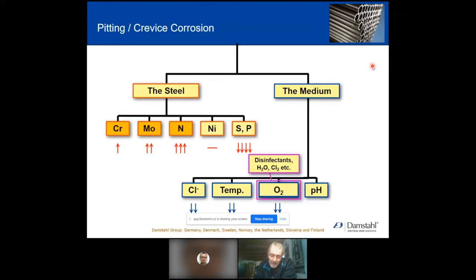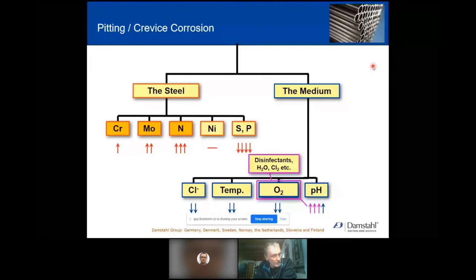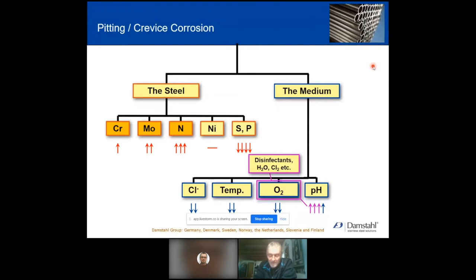pH doesn't have any big effect on the steel. The higher pH, the better. But what's very important is that pH has a tremendous effect on, for instance, the oxygen reaction. So pH actually becomes quite important, and pH 8 is definitely worse than 9, which is worse than 10. Finally, anything else could be all kinds of proteins or inorganic matter. If they don't affect either the chloride, the halogenates, or the cathode reaction, normally it doesn't really matter. Yeah, these two are the key ones.